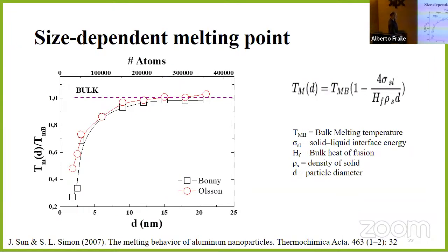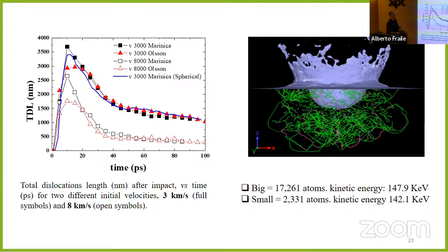So this is what I was saying before, the melting point divided by the melting point of the bulk material has this depression here. Then for big enough particles, the ratio goes just to 1. And there are different models like that. So it's also expected to have some disagreement at the very low end, when you use very small nanoparticles as impactors. And then about the total dislocation length in the target, this is the movie I showed before.